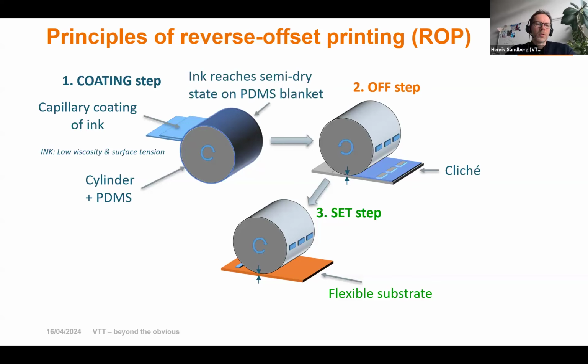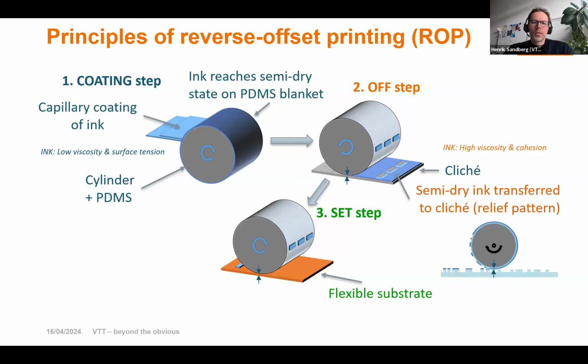The ink has to remain in a semi-dry state on the cylinder, so that's why the PDMS properties are important, because some of the solvent is absorbed into the cylinder or into the PDMS film, and some is of course evaporated, and that semi-dry state has to be stable for some time, so that this off process happens reliably.